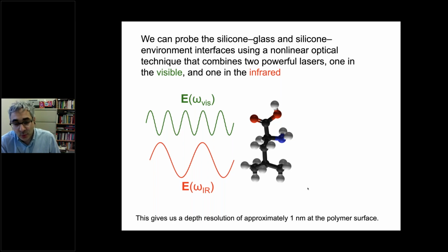And basically what we do is we use two lasers, and I'll show you a photo of the setup in a second. One of the lasers is in the visible at 532 nanometers, and one of the lasers is in the infrared. And when you come in with two pulsed high power lasers and you overlap those beams on the surface of the silicone rubber in space and in time, something very special can happen. What can happen is, in addition to the normal phenomena that you would observe, those two photons can be annihilated.